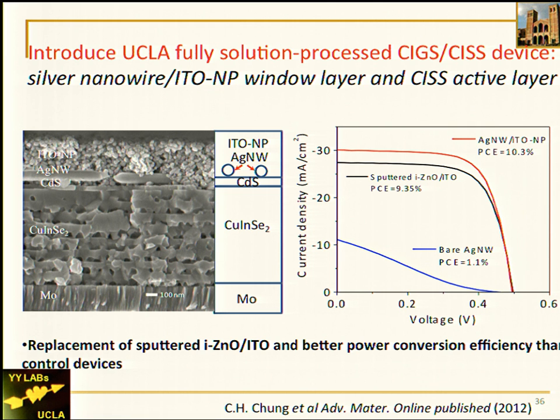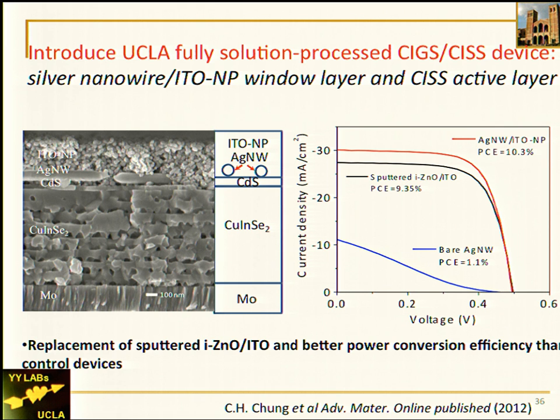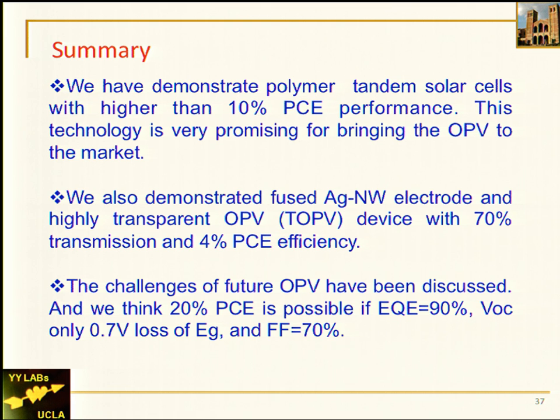With our silver nanowire electrodes, we have demonstrated a fully solution-processed stack from bottom to top except for the Mo layer. We could potentially go to Santa Barbara, borrow Maria's coater, and print the CIGS solar cells — turning DuPont Display into DuPont Solar Energy. This completely changes the manufacturing pyramid for inorganic solar cells. The red curve (solution process) actually performs better than the black curve (sputtering process). We also applied our solution-processed window layer to tri-stage CIGS cells from NREL and the performance is more or less the same — a very important achievement borrowed from OPV and applied to the CIGS field.